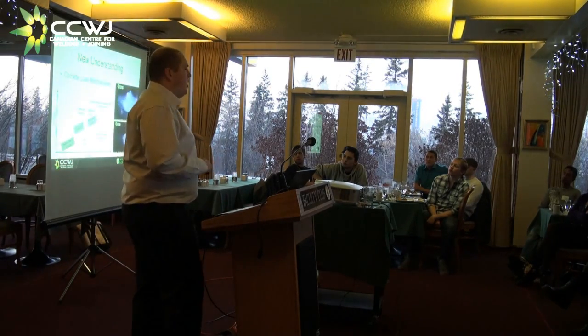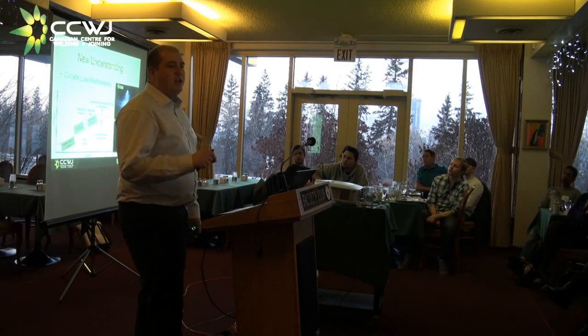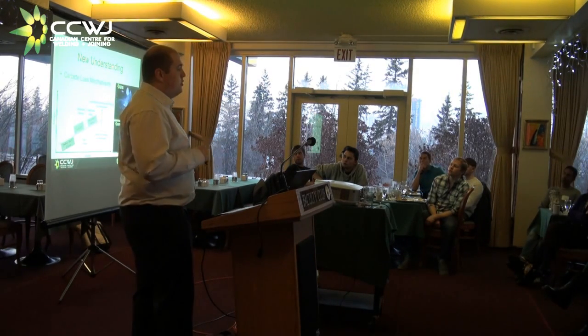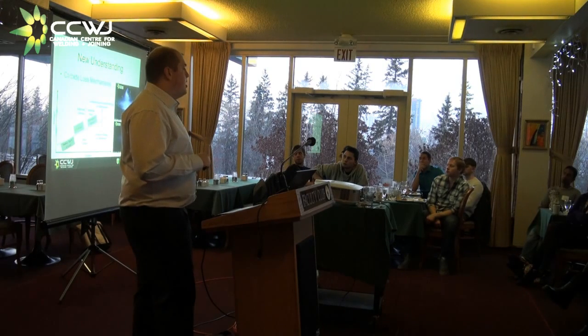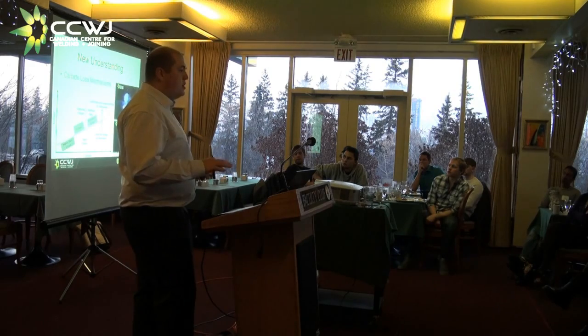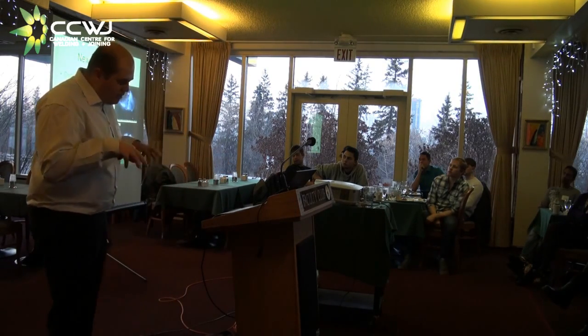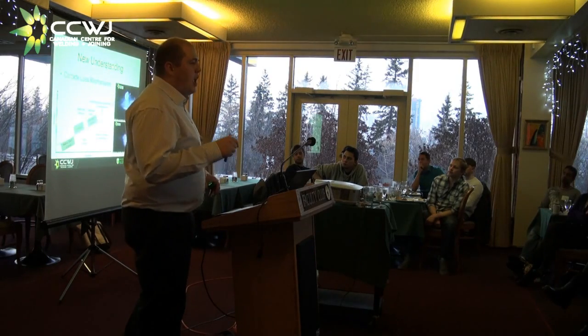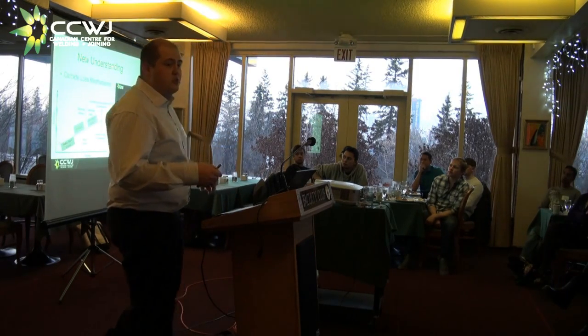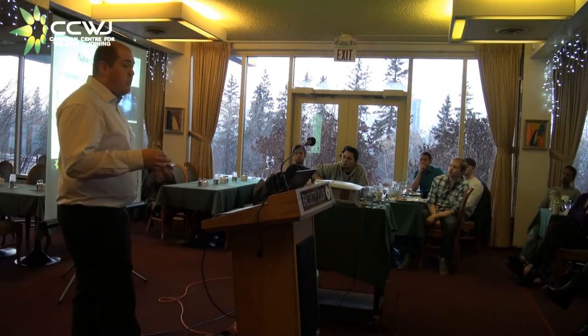Basically, what we found, specific to MIG overlays, gas metal arc with these tubular wires, is that tungsten carbide is non-wetting. Now, this was previously maybe theorized. We saw some carbides on the plate afterwards, but we didn't know the degree of the problem. And while using our high-speed videos, we found this to be an actual big problem.